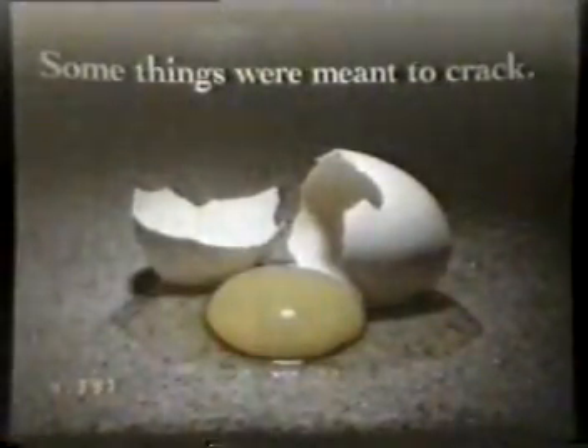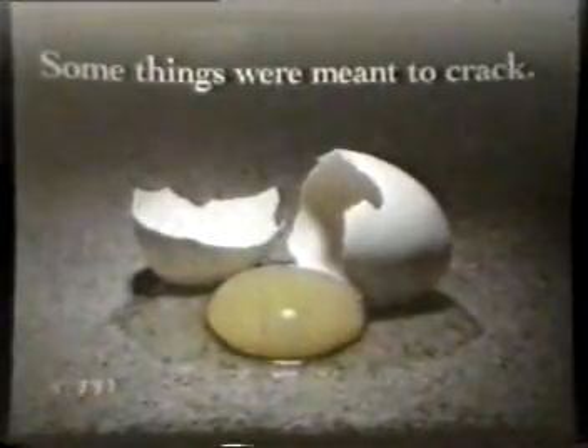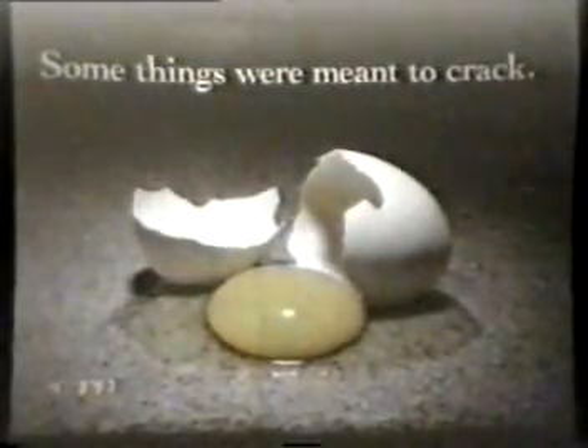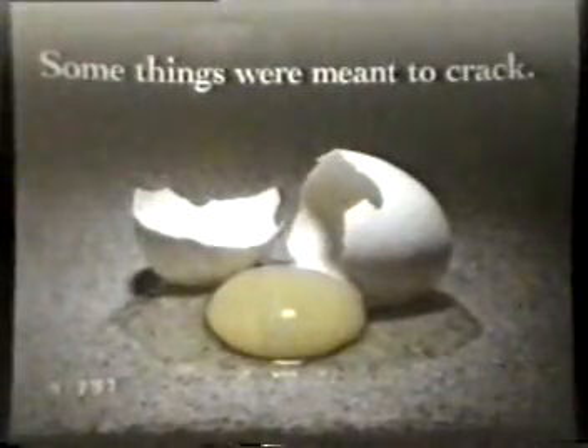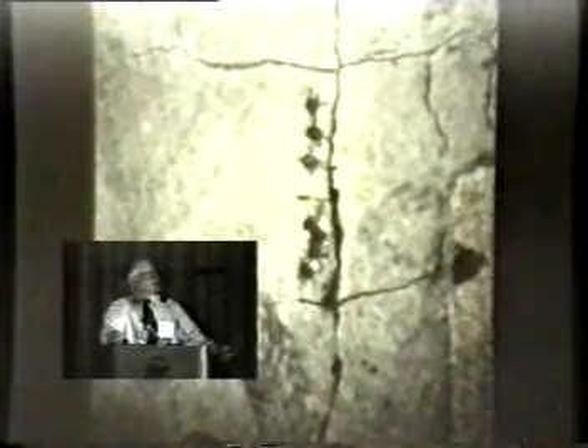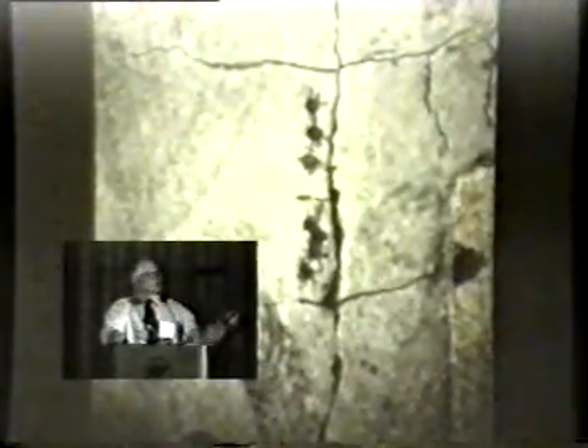I stole this from the bulletin. It was an advertisement from one of the booth presenters. I thought it was really good. Some things were meant to crack, and certainly our repair material is not designed to crack, but it does. It's a problem, and we've talked a lot about that over the years. And certainly when a repair material cracks, it opens up a canyon for these materials to go right back into the reinforcing steel. So we have an issue with that, big issue. So no matter how good this material is between the cracks, it's absolutely worthless if we have cracks in it, if the cracks allow the moisture and salts to penetrate it.